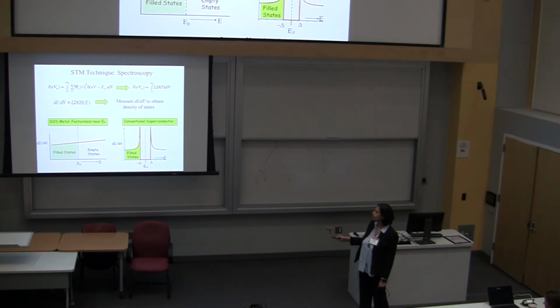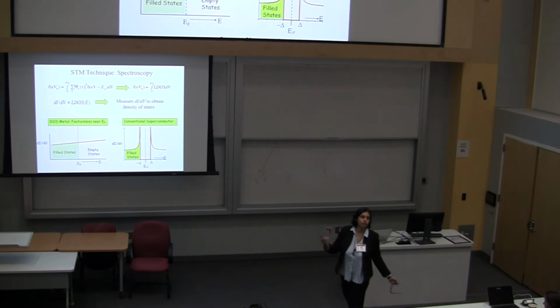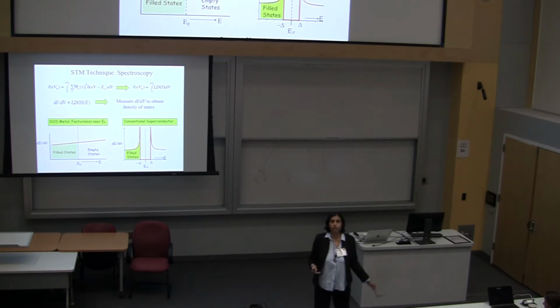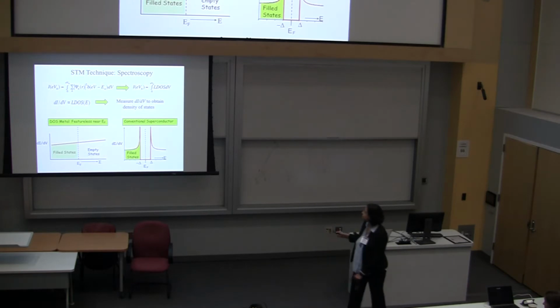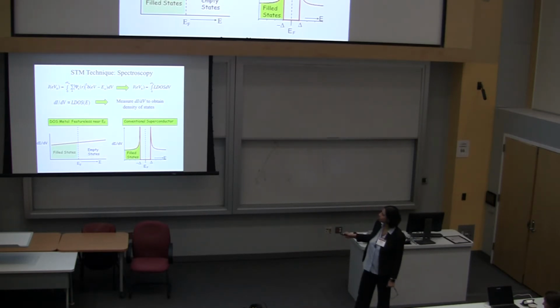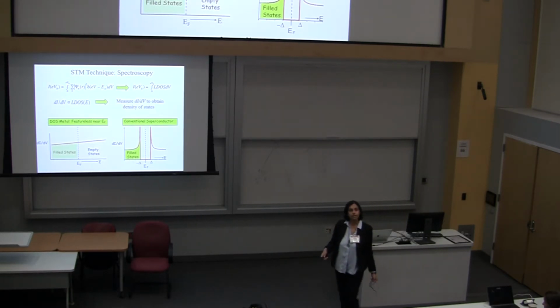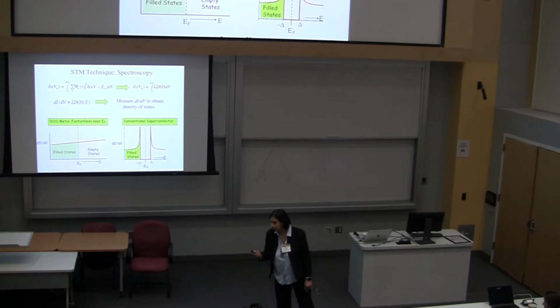So for example, if you would put your tip at one point and measure dI/dV for a normal metal, here's the Fermi energy, this is zero bias, you would simply get a flat straight line across the Fermi energy, so metal is pretty boring. Whereas in a superconductor, you would see no density of states at the Fermi energy, and then you would see these coherence peaks on either side. So that's what STM spectra look like.